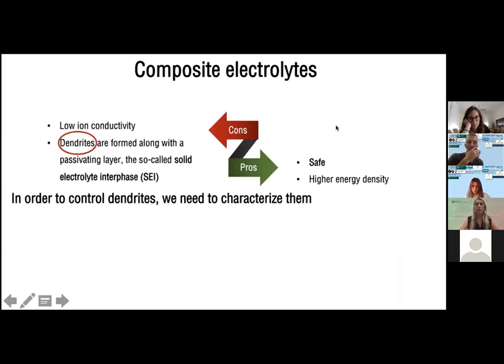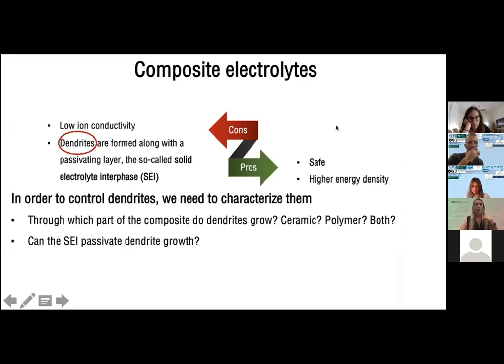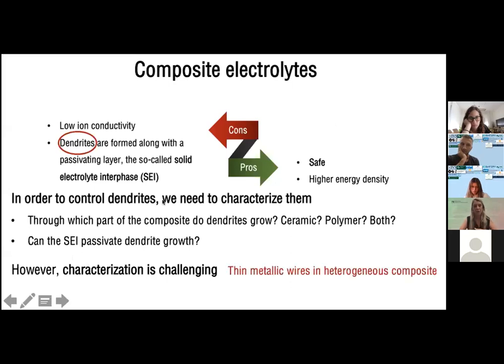And in order to control them, we have to characterize them. Especially we need to answer the question through which part of the composite these dendrites grow and propagate. If it's from the ceramic part, the polymer part, maybe both of them, and can we grow some SEI that can passivate the dendrites from continuing to propagate and short circuit our sample. However, characterization of these dendrites is really challenging. They are thin metallic wires in a heterogeneous composite that are very reactive and you cannot expose them to air. So today I'm going to present how we can do that using solid state NMR.